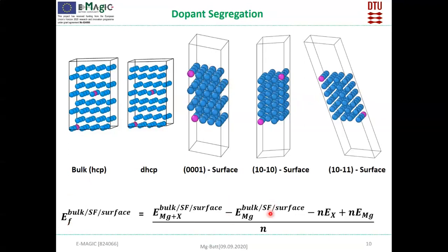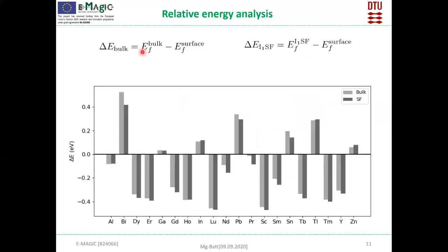And this is a similar equation which is used for the stability analysis. Then we compare based on these 2 equations. So these 2 equations are made from the formation energies. And this delta E bulk means the energy of formation when the dopant is in the bulk minus the energy of formation when the dopant is in any of the surfaces. And for the stacking fault, it's the energy of formation in the stacking fault minus the energy of formation in the surface. So what we want